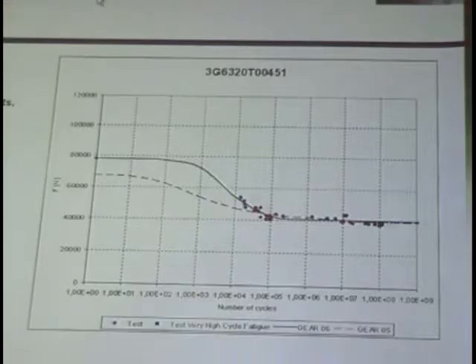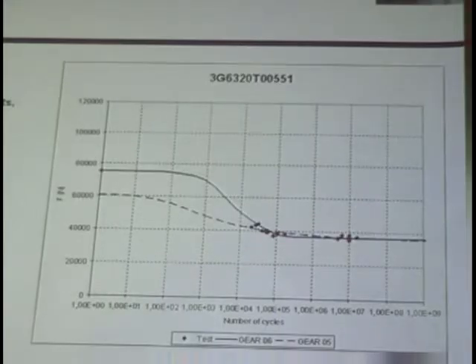shot peen. And here you see that we have tests up to 100 million cycles, and in this range we have had 2 failures. In the data fitting, all the points have been considered as failures, because the fitting of the curve has been done by the standard least square method. Here you see that we have 1 point which represents the ultimate load. So we forced the curve to pass through that point, and then we made the data fitting on the other tests. Of course, you cannot rely on this part of the curve because it's meaningless, but this part is currently represented by the formula which is currently employed in the practice of designing transmissions in this industry.